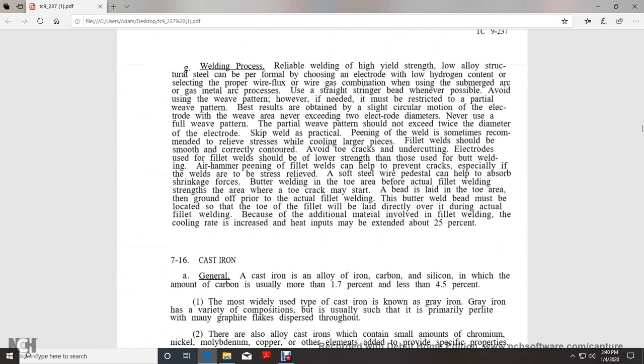Welding process. Reliable welds with high yield strength and an alloy structure can be performed by choosing an electrode with low carbon, low hydrogen content, and selecting the proper wire, flux, and wire gas combination when using submerged arc or gas metal arc processes. Use a straight stringer bead whenever possible to avoid using a weaving pattern. However, if needed, use a restrictive partial weave pattern. The best results are obtained with a slightly circular motion with the weave never exceeding two electrode diameters. Never use a full weave pattern. The partial weave pattern should not exceed twice the diameter of the electrode.